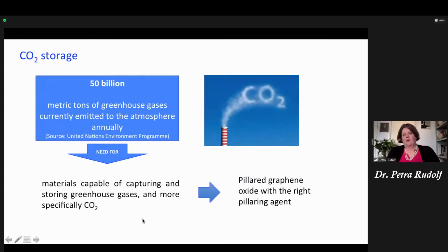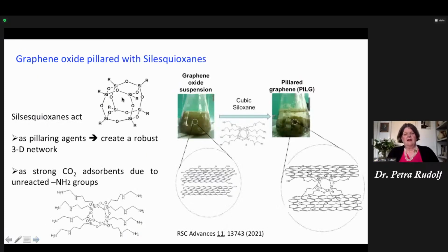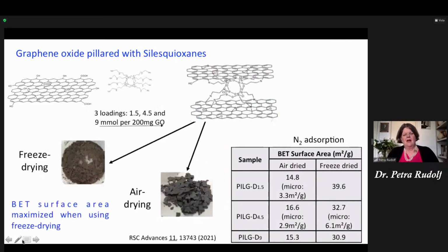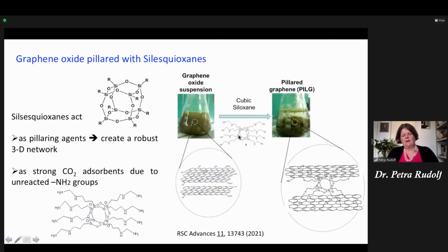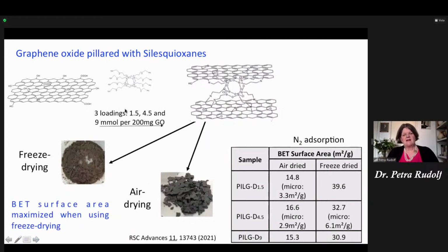CO2 storage, you know the problem, billions of metric tons emitted in the air annually. Can these pillar structures help? Well, what we use as a pillar here is little silicon oxide cubes. Actually, they also have these ligands on them, and we put them again between the graphene oxide layers. That's something that we have just published now, and we look how it does for CO2 storage. And we actually dry it by freeze drying and by air drying, because we wanted to know which surface area you get. A bigger surface area in this case is more effective.